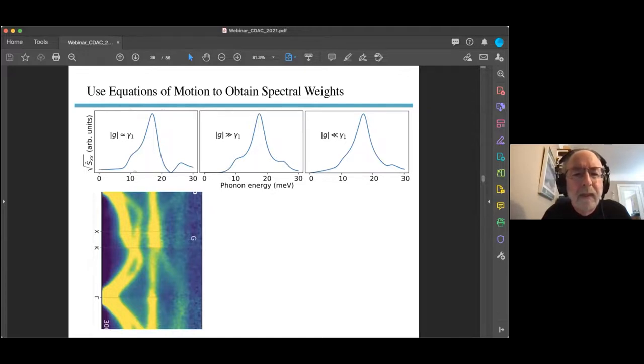It's on a shoulder, effectively. So we think this works reasonably well. We did see these ghost modes in the anharmonic calculations with the temperature-dependent effective potential method, but they were way too weak in intensity. This one gets the intensities about right, it turns out, when we're in the medium coupling limit.